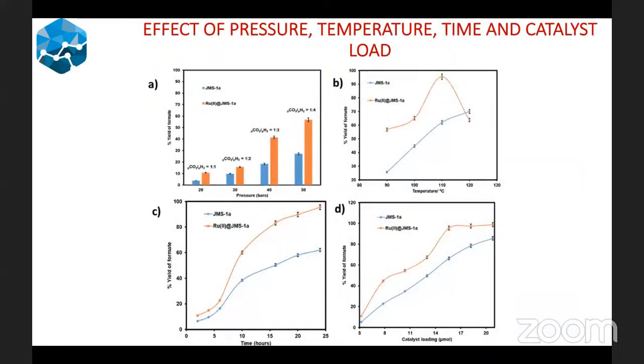And of course, during catalysis, we have evaluated different parameters for hydrogenation of carbon dioxide to formate. We looked at the effect of pressure. As we increased the pressure, we realized that the yield of formate that is produced also increases. And of course, an increase in temperature also results in an increase in the yield that is formed. So here we have the ruthenium functionalized MOF, which is being compared to JMS-1a, which is the pristine MOF.